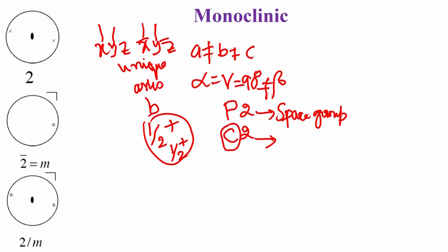The next system which we will take up is the point group symmetry corresponding to the mirror plane. In this particular case, as you will see here, there are different kinds of notations. If we write the mirror symmetry like that, that means that the mirror is now in the stereographic projection equatorial plane, which means that the mirror is in the plane of our presentation, and you see here that the x, y, z and the generated mirror component, which is x, y bar, z, are on top of each other.